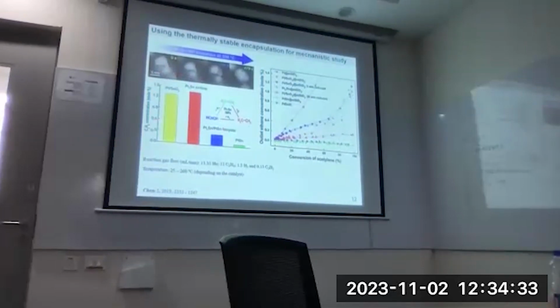So with our catalyst, we tried to show that the adsorption behavior of this is completely different on our intermetallic compounds compared to just platinum. If you use platinum, it's going to just fully hydrogenate to ethane. You're not going to be able to control the hydrogenation, right? In the platinum tin, there are very low amounts of ethane forming. Almost all of this is being converted to ethylene, because again, you can only form a weak interaction of this on the diluted platinum surface, right? And so you get almost 100% selectivity to forming the ethylene, and then you can go to the next step of polymerization, right?